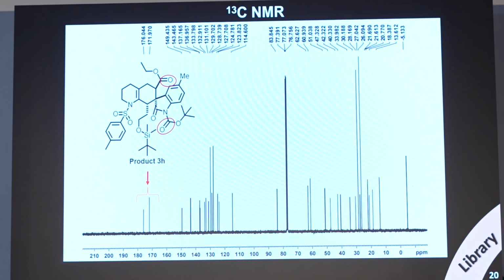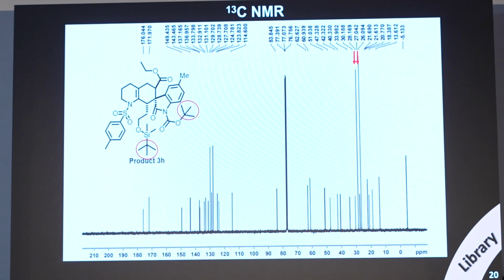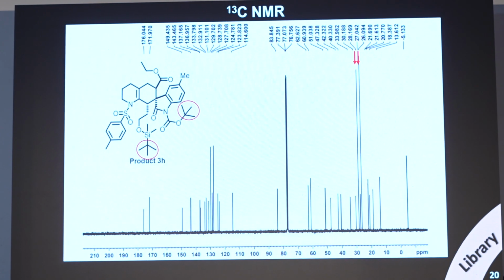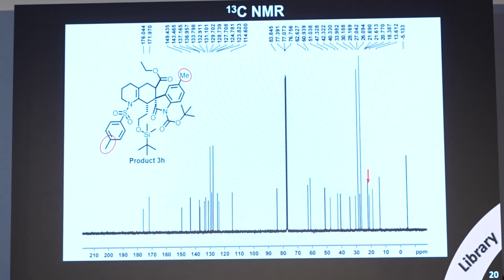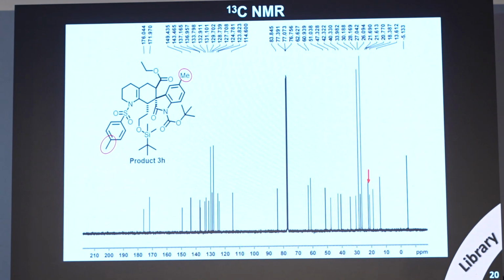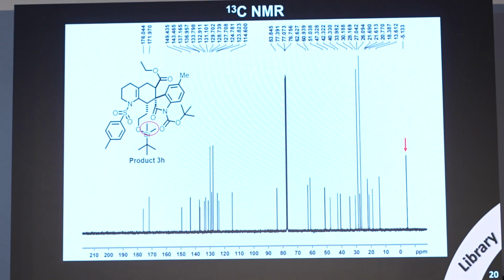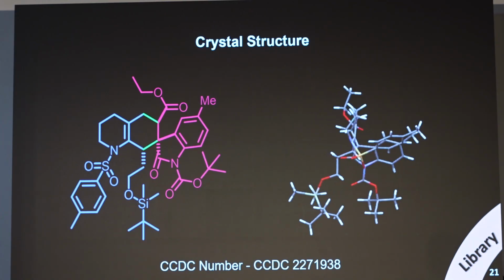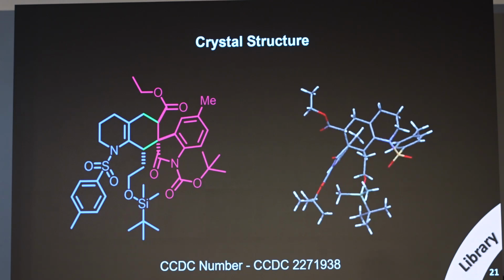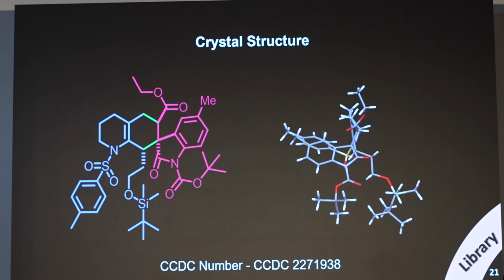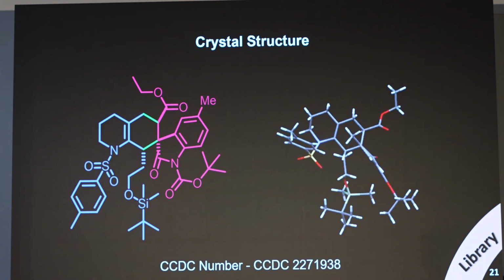Here this carbonyl peak resonates at around 170 to 180, and this amide carbonyl resonates at 150, and these two tertiary butyl resonate at around 30, and these 2 methyls resonate at 22. And this silyl methyl resonates at -5. To understand the stereochemistry of the compound, this is the crystal structure of the compound. From this crystal structure, we came to know the configuration of this molecule.